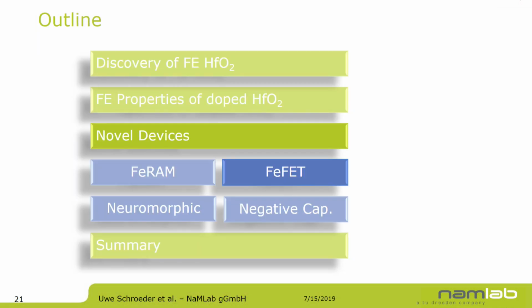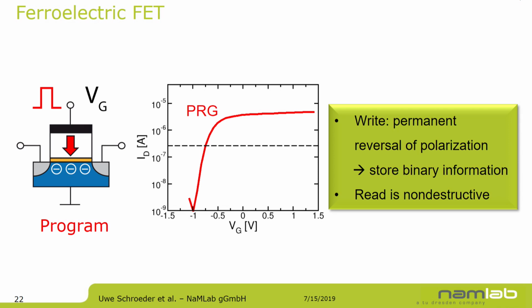Okay, so this was the first device. The second device would be the transistor. Basically, we took a GlobalFoundries transistor, which is a high-performance transistor for the newest chip generations, and in this case, just to make it more simple, a planar transistor, 28 nanometer ground rule. In the high-performance transistor you have like 2 nanometers of hafnium oxide in between a TiN electrode and your silicon substrate with a thin silicon oxide interfacial layer. You replace this 2 nanometer hafnium oxide by 8 to 10 nanometers of ferroelectric hafnium oxide.